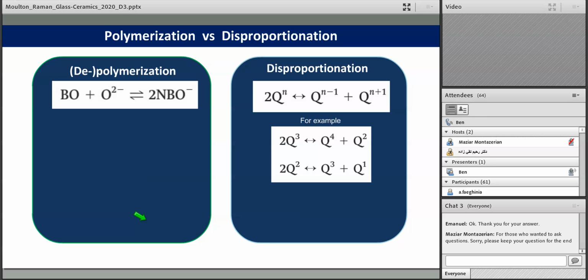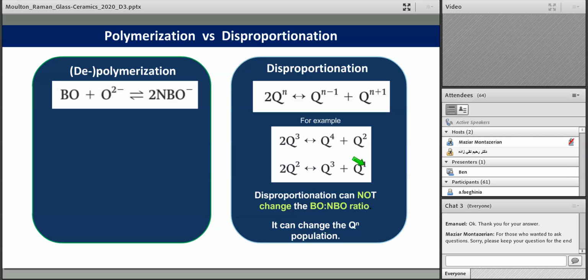The much more common reaction you'll see is the disproportionation reaction: 2 Qn goes to Qn-1 plus Qn+1. For example, if you have two Q3s, they can disproportionate into a Q4 plus a Q2, or if you have two Q2s, they go to a Q3 plus a Q1. It's important to note in these cases, if you look at the number of non-bridging oxygens, let's take the top equation here. There's our Q3, so there are 3 bridging oxygen, which means there's only 1 non-bridging oxygen, and it disproportionates into a Q4 with no non-bridging oxygen and 2 non-bridging oxygen on a Q2 species. So these disproportionation reactions cannot change the ratio of bridging to non-bridging oxygen, but they can change the distribution of Qn species.